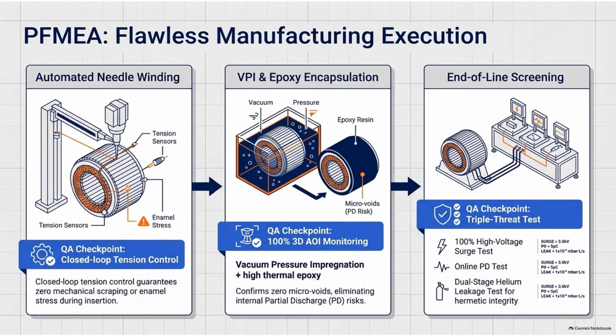And what happens if the vacuum isn't perfect and a tiny bubble of air remains trapped in the epoxy? A bubble is catastrophic. After the resin cures, the factory uses 3D automated optical inspection, or AOI, to guarantee a 100% fill rate. Okay. If there's a microscopic void, a bubble, it means trapped air. In a high-voltage environment driven by silicon carbide, that trapped air pocket has a lower dielectric constant than the surrounding epoxy. The electric field concentrates inside that bubble, ionizing the gas and creating a persistent internal partial discharge. A tiny plasma storm trapped inside an epoxy bubble, slowly chewing its way out until it causes a short. Exactly. Okay. So the vacuum and the AOI ensure absolute zero voids.